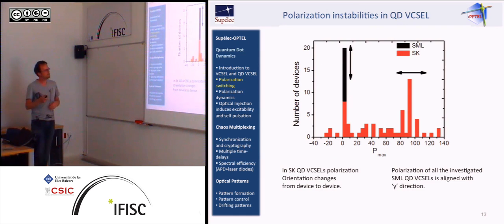So these are the experimental results on a few hundreds of devices we got. And we got two classes of devices. Some of them were grown, the dots were grown by a submonolayer technique, and some of them were grown by the Stranski-Krastanov technique. And basically what we observed is that the Stranski-Krastanov lasers have a large distribution of the polarization states where they want to emit the maximum power.